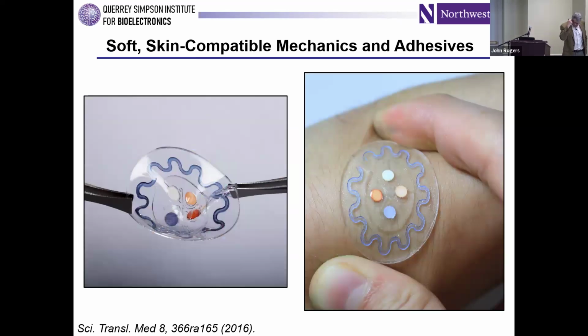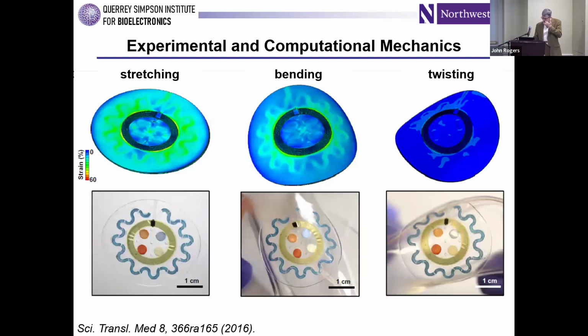So like with the electronics, it's really important to think about mechanics and adhesion and soft materials integrated with the skin. In this case, maybe even more challenging than the electronics and the applications I mentioned before, because now you're thinking about integration with the skin in the context of what could be vigorous rate of sweating and also pretty extreme mechanical motions of the skin. And one way to solve that is just use super glue. You really adhere it tightly to the skin, and that way removal becomes a problem. The other way to do it is to make the device as soft as possible and as thin as possible. And if you do that, you reduce the interface stresses that would otherwise tend to drive delamination, thereby making it much easier to establish a robust adhesive interface to the skin.